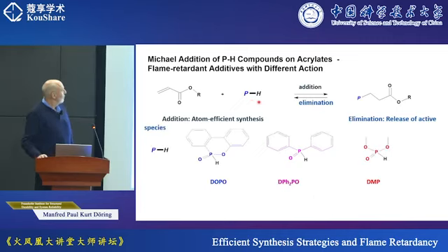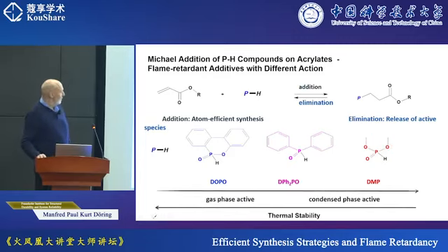Okay, of course we can do this not only with DOPO. Here we have a DOPO, here diphenylphosphine oxide, and here phosphite. And of course these represent different effects. Here much more in the gas phase, here more in the condensed phase. And the thermal stability is growing in that line.